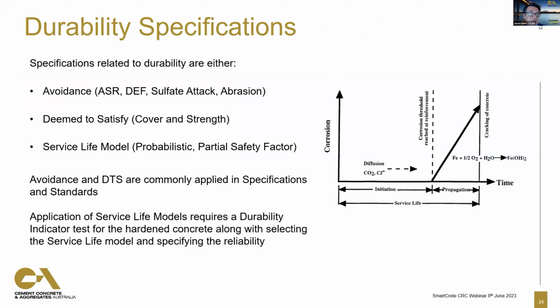And in durability, we really talk about three ways that we control durability of concrete. We have avoidance. We have rules about don't do this, this, and this, and these mechanisms of concrete degrading won't occur. We then have deemed to satisfy rules like cover, reinforcement cover, and minimum concrete strength requirements. And then we move to things like service life models, probabilistic or partial safety factor service life models. Avoidance and DTS are really common in specifications and standards because the service life models do require a more thorough understanding. It's more complex. You need to have a durability indicator test. You have a service life model you have confidence with, and you need to understand the mathematics to ensure that you get the reliability that you're looking for.